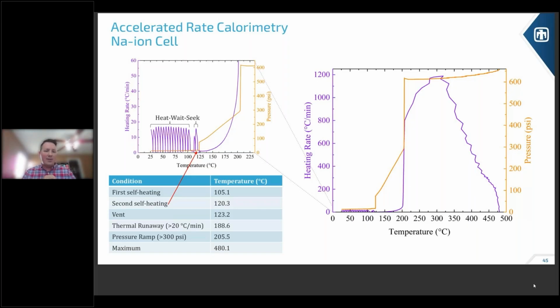We see one self-heating event at 105. So this one is not strong enough to make the cell go into runaway. So the system goes back into heat-wait-seek. We see another self-heating event at 120. Now this one does sustain. It leads into a vent, and then a thermal runaway at 189. A pressure ramp, and then our maximum temperature of 480. So now you can go ahead and go straight through to the next slide.